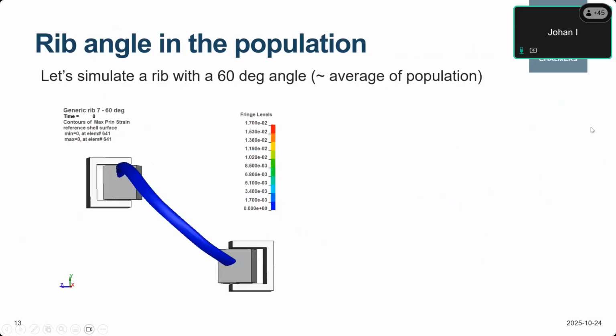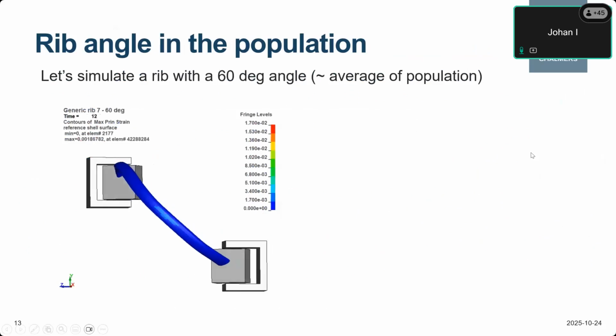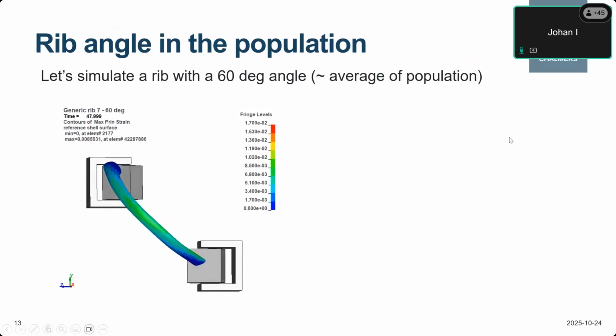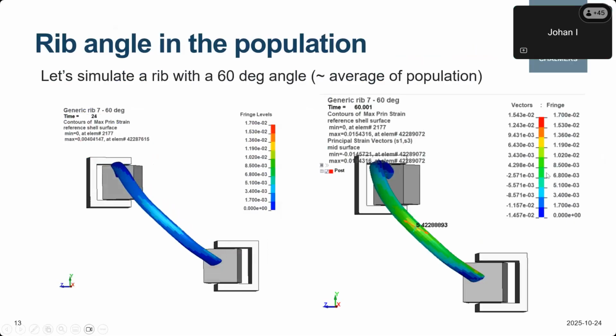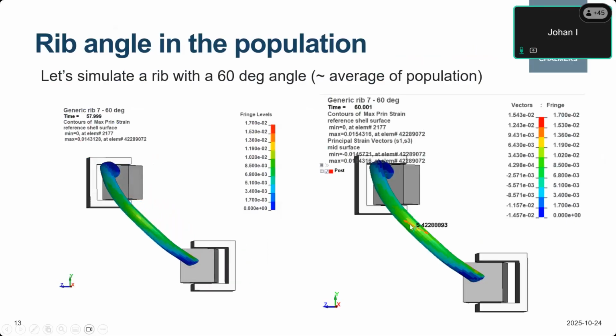So let's test what that means. If I then rotate the rib to a 60-degree angle, which would be somewhere around the average of the population, we run the simulation again, and we then look at the principal strain vectors here. Now we can see that it's not following along the direction of the rib and along the direction of the osteon. So now we have rotated it a bit, and that means that it's not only loading in the direction of the strong bone, but also in the perpendicular direction that is much weaker. So in this case, there is a risk that we underestimate the fracture risk.